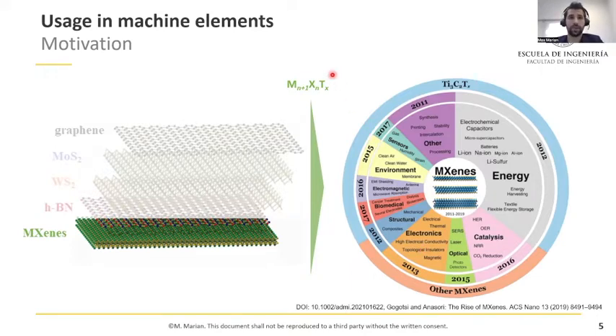MXenes are denoted by the general formula M_{n+1}X_nT_x, where M stands for n+1 layers of an early transition metal from groups 3 to 5 in the d-block of the periodic table. X_n stands for n layers of carbon, nitrogen, or a mixture of both, and T_x for the variety of surface terminations. The most prominent representative of MXenes is Ti3C2Tx.